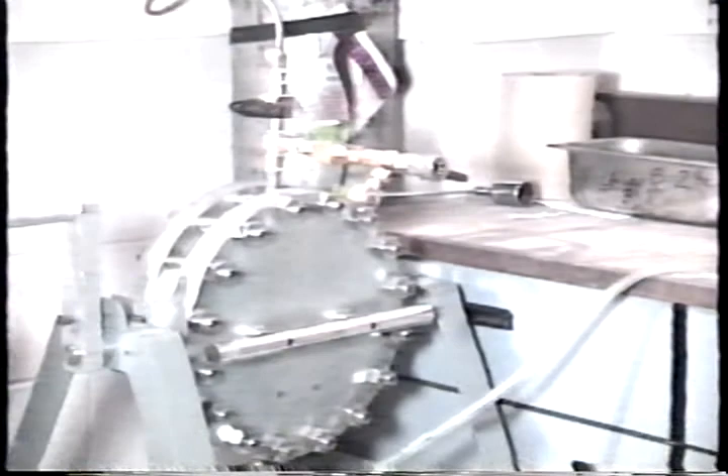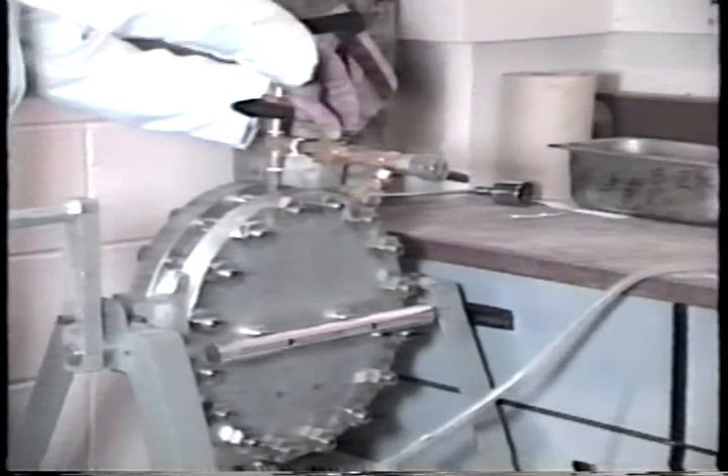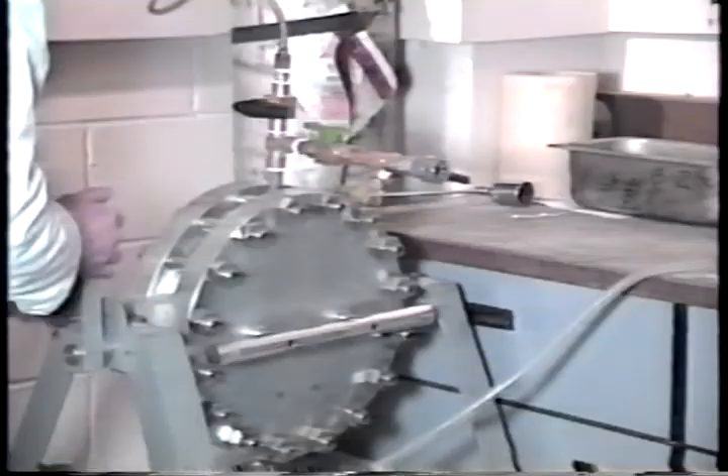The hydraulic fracture test is based on the assumption that hydraulic pressures produced in concrete by freezing can be simulated by subjecting aggregates submerged in water to high pressures. When the pressure is released, the air compressed in the pores of the aggregates expands and pushes the water back out. Fracture occurs when the water cannot be released quickly enough.